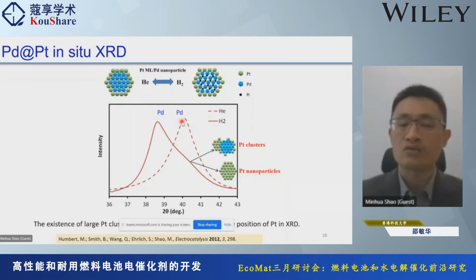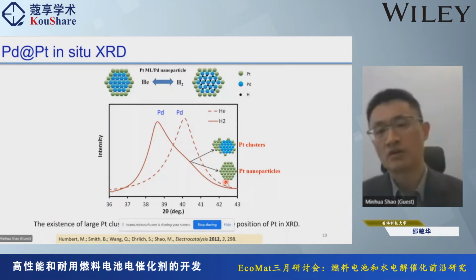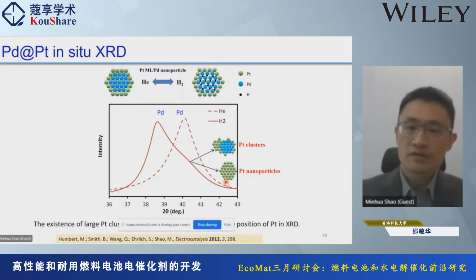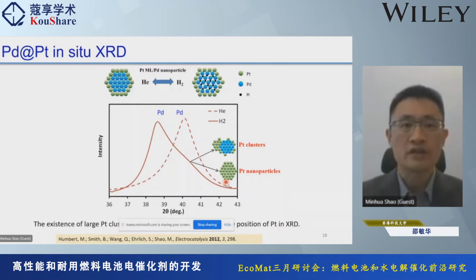So the X-ray diffraction peak shifts to a lower angle for palladium. But if you have large clusters of platinum on the palladium nanoparticle, you will see a shoulder here. This shoulder will not leave the original place. So we confirmed that in our mass production we had this problem, the formation of platinum large clusters on the nanoparticles. So this is quite a useful technique to assess the quality of our core-shell catalyst.